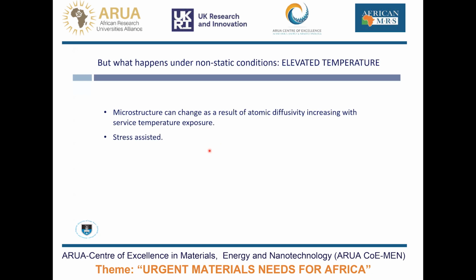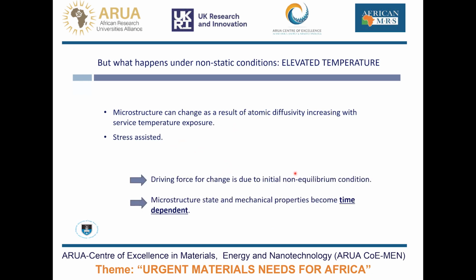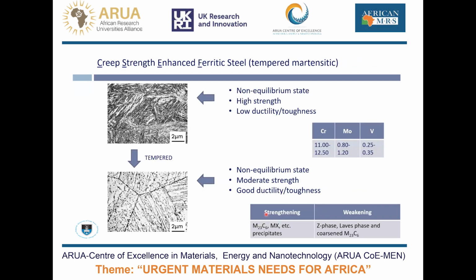Of course, what happens under non-static conditions, in other words, elevated temperature, as you would get in a power plant? Well, microstructure can change as a result of atomic diffusivity, increasing with service temperature exposure, and of course, it can be stress assisted. Now, this driving force for change is due to the fact that the metal, in this case, steel, is deployed in the initial non-equilibrium condition. And therefore, if you give it enough exposure to an environment where diffusion can occur, stress can assist those microstructural changes, the microstructural state and mechanical properties, of course, become time dependent. And the situation gets a lot more complicated.